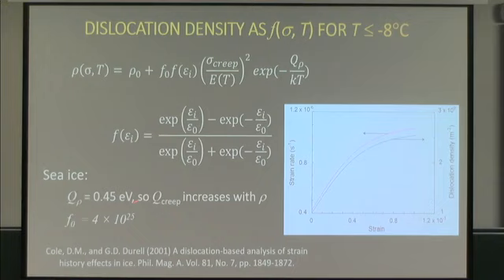The other interesting thing here is we also found that the dislocation production has its own activation energy. This has real important implications more in glaciology than in sea ice mechanics, because that crowd has been wrestling for years with all these seemingly unexplainable variations in activation energy. But this model, these values are a little different in freshwater ice, I'm finding out. But basically, if you have a really low stress situation, you're not producing dislocations to any great extent, you have a relatively lower activation energy, the temperature dependence. As you go to higher stresses and produce more dislocations, especially for sea ice, your activation energy can get up to around 1 eV, whereas if there's no production, it's less than half of that. So the temperature dependence of this model and the constitutive behavior of sea ice depends very dramatically on how many dislocations are produced.